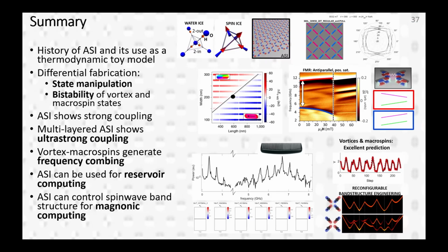Yeah, Olivia, so I guess nanoseconds, just like typical magnetization reversal timescales. But some people do super paramagnetic artificial spin ice where you make them very thin, so then they can be manipulated by temperature, but I'm not sure what the timescales there are, but I imagine they're faster.